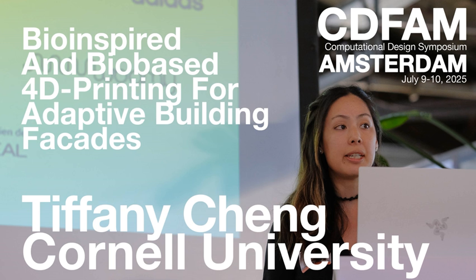So how do we program shading for the different seasons using a humidity reactive material? So in temperate climates, such as in Germany, but most likely here in the Netherlands as well, there's a reliable link between temperature and humidity. So if you take a look at a typical winter day, you can see that the humidity in blue remains quite high, while the temperature in red maintains a very low trend. And on a typical summer day on the right, you can see that there's much more daily fluctuations in temperature, but the humidity always maintains this inverse relationship. And so we had to design our shading elements to curl and open when humid and then flatten and shade when dry.